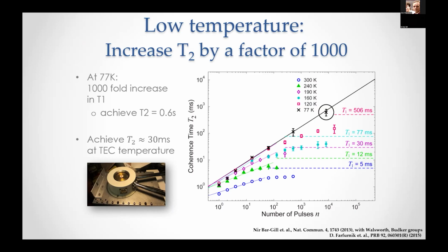Okay, so just to summarize, it's important to take into account all of the different noise mechanisms, but what this experiment shows is that we're dominated by spin noise. Actually, in this system, it was a dense diamond, so we were dominated by nitrogen impurities in the lattice, which create spin noise, which we can then suppress by applying these CPMG sequences.